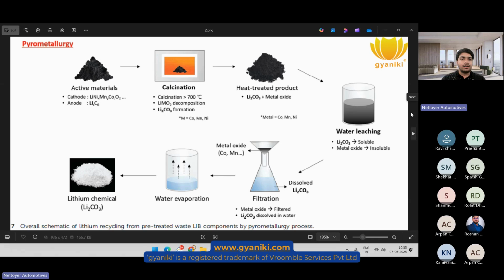So initially we have got the picture that we have active materials. Active materials basically constitute black mass. Now this black mass is being heated with the calcination process that will go beyond 700 degrees Celsius, and it will have some decomposition and formation as well. Now this preheated material goes under water leaching, and after water leaching we have further processes to extract lithium carbonate. Lithium carbonate is the core aim material. That's the thing we have to extract.